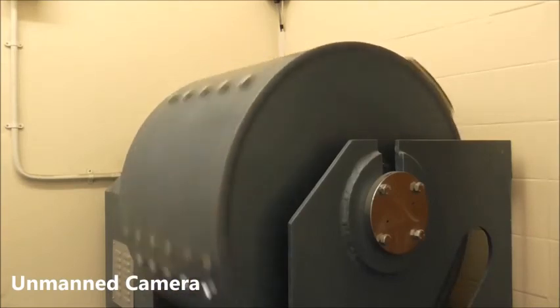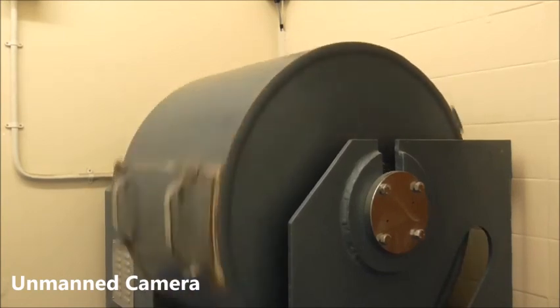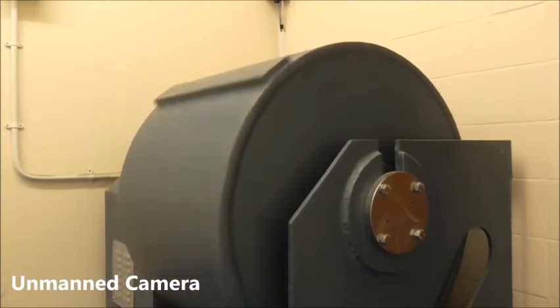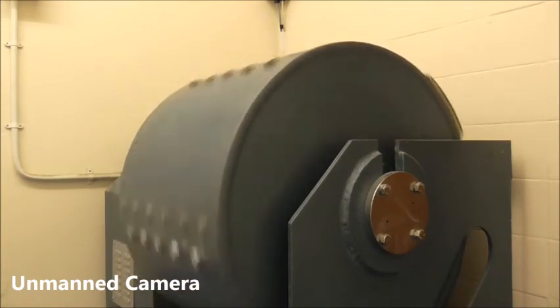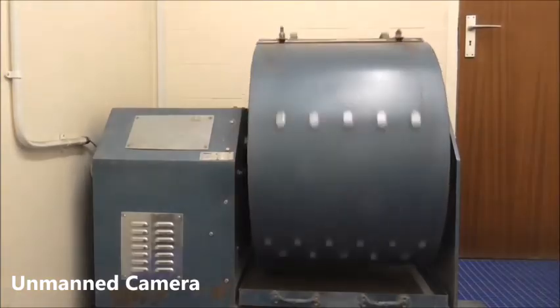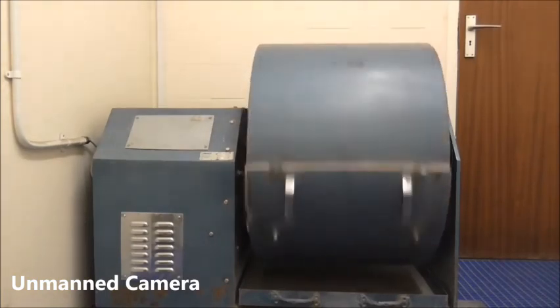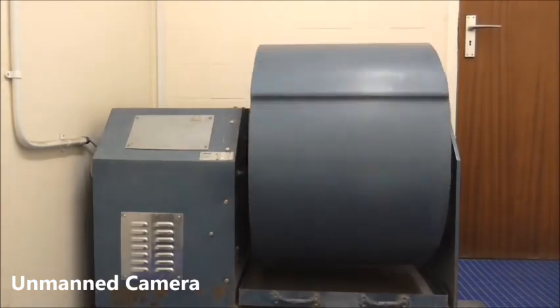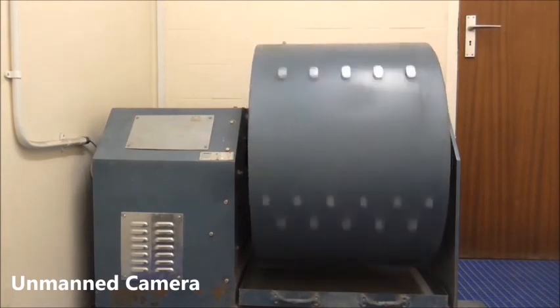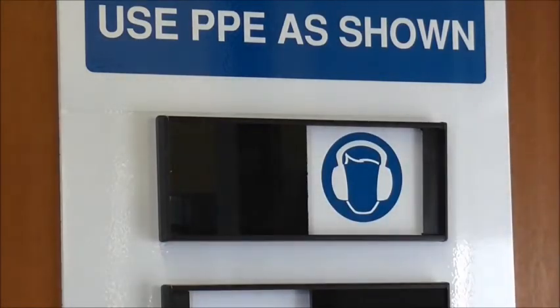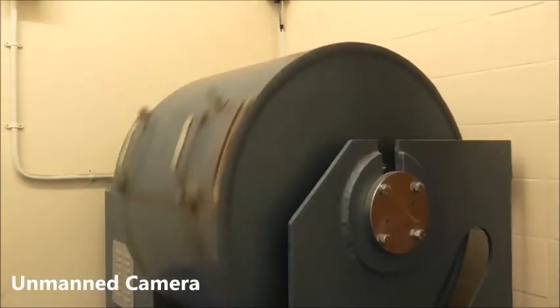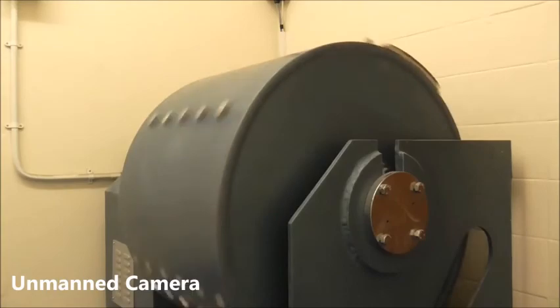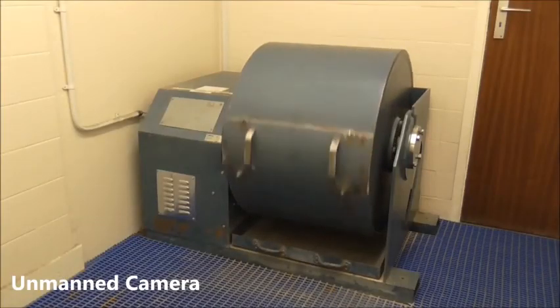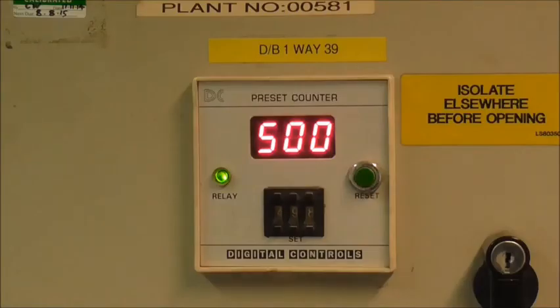Inside the drum is a metal shelf that lifts the aggregate and balls, which in turn causes the aggregate to become fragmented. Each ball must have a diameter of between 45 and 49 millimeters and a mass of between 400 and 445 grams. The test is noisy, therefore anyone directly outside of the room must wear ear protection. The test requires the drum to rotate at a speed of between 31 and 33 revolutions per minute. Therefore, it takes about 15 minutes for the drum to complete the 500 revolutions.